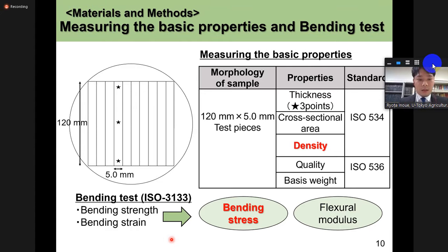We measured thickness and quality and then calculated the cross-section area, apparent density, and base weight. The 3 black marks are where the thickness was measured. We performed a bending test using these test pieces. The bending test gave bending strength and the bending strain. We calculated the bending stress and the flexural modulus from those values. For the sake of time, I'll talk only about the density and the bending stress measurement results.